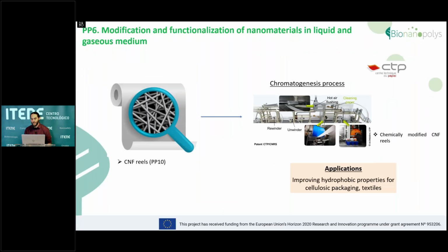This pilot plant 6 also has the capabilities of the patented process by a CTP partner of ours, which allows us to functionalize the surface of paper. In this case, it could also be paper reels made with cellulose nanofibers. And by depositing on it hydrophobic molecules that will bring oil repellency and improved barrier properties to the paper without the use of solvents.